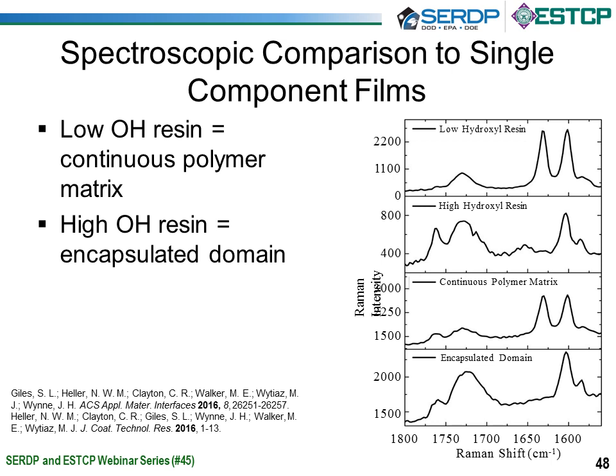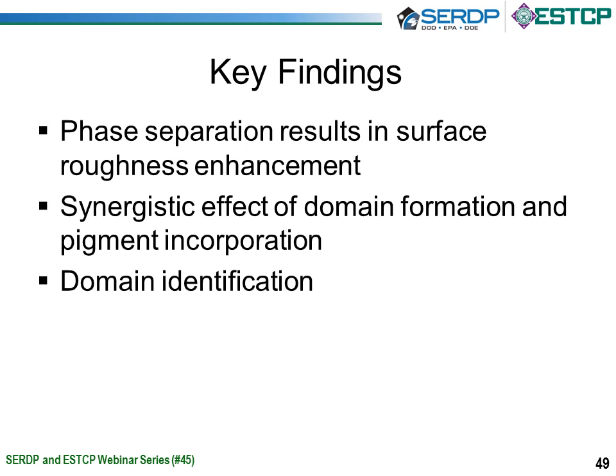So finally, in slide 49, to recap some of our key findings, we've demonstrated that phase separation results in surface roughness, in both clear and pigmented films. We've demonstrated a synergistic effect of domain formation and pigment incorporation. And finally, we've been able to identify the domains themselves and their composition, and associate a low or high OH with the corresponding domain, pigment and continuous film. And that concludes my portion.